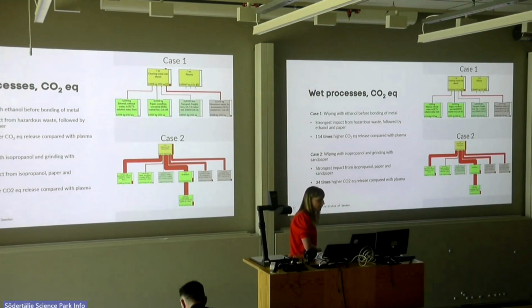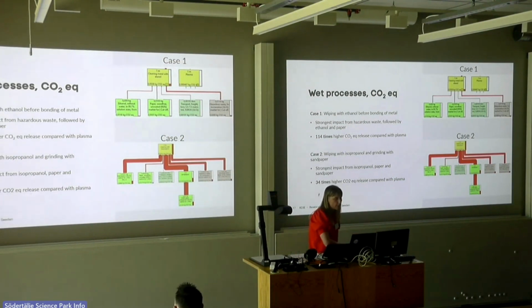So I mentioned in the beginning the benefits of using dry processes compared to wet. We have done some smaller studies here. It's not in process baths, but we compare cleaning manually with a cloth with ethanol compared to using plasma of the type on the previous picture. So 114 times higher CO2 equivalents when using the ethanol solvent. And case 2, with isopropanol and using sandpaper for grinding, you also have 34 times higher CO2 equivalent. So these are some examples, but there is so much more to do in this field to compare.